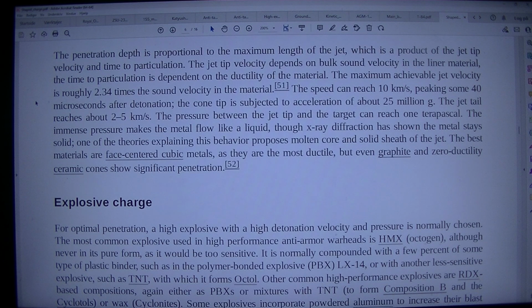51. The speed can reach 10 km/s, peaking some 40 microseconds after detonation. The cone tip is subjected to acceleration of about 25 million g. The jet tail reaches about 2-5 km/s. The pressure between the jet tip and the target can reach 1 terapascal. The immense pressure makes the metal flow like a liquid, though X-ray diffraction has shown the metal stay solid. One of the theories explaining this behavior proposes molten core and solid sheath of the jet.